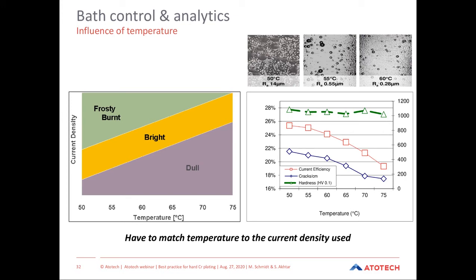So always the temperature and the current density have to match. This means actually there is a certain area where the chrome is plating bright. This is the yellow field in the middle. And when you want to plate faster and you increase the current density, the chrome would usually burn or get this roughness.